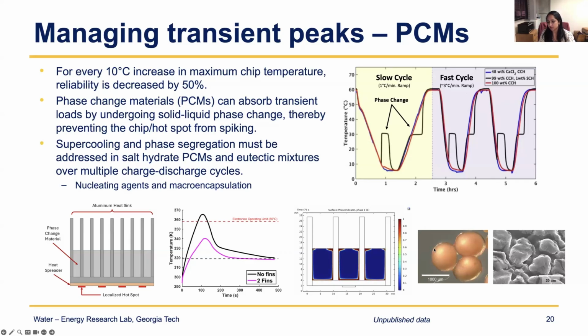And then we encapsulate the phase change materials. So the PCM is within this shell, and that shell is just preventing the material from leaking out as it melts. So that way you're working with these smaller spheres of phase change material that can melt and solidify quickly rather than a large amount of the PCM. So that's just a macro encapsulation technique that we use.